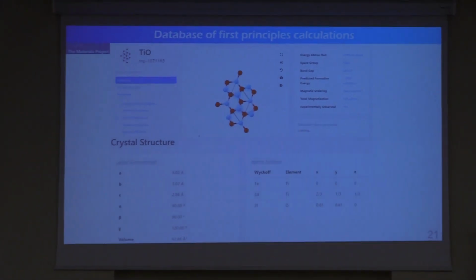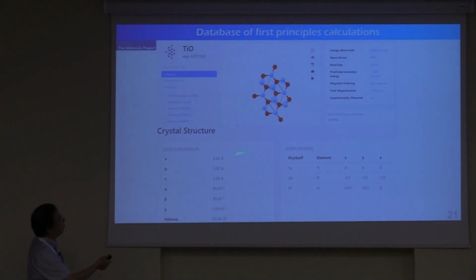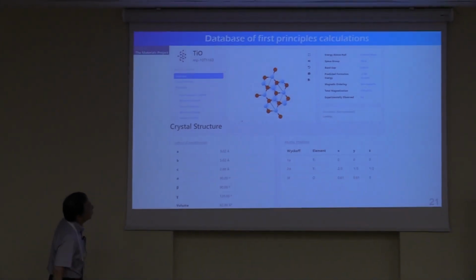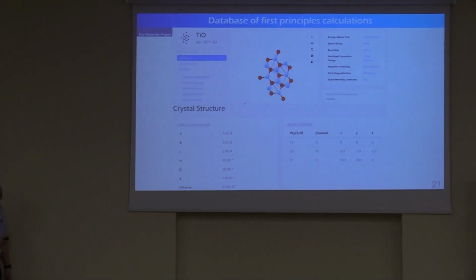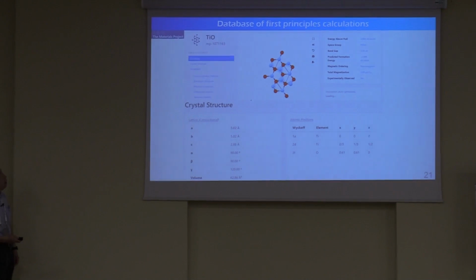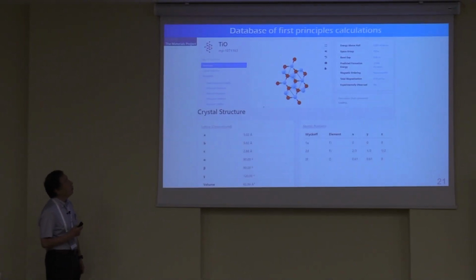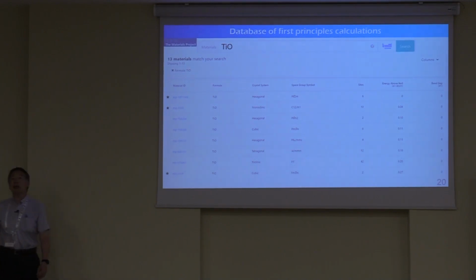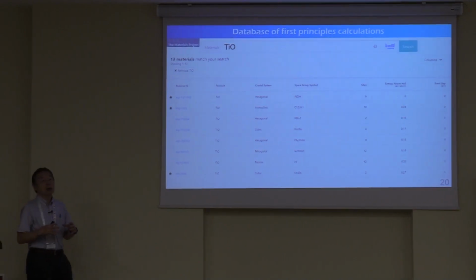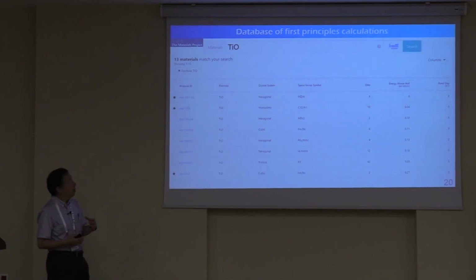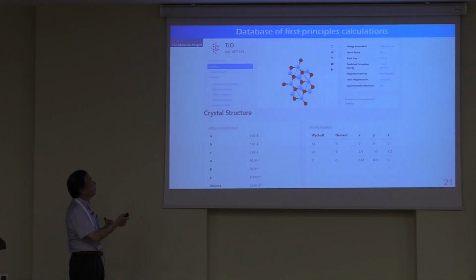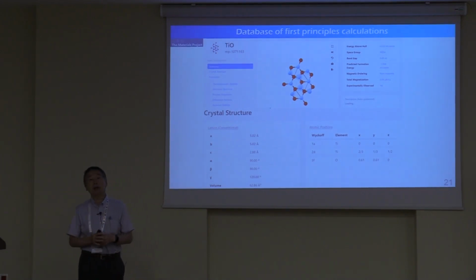The structure can also be drawn within the database. It looks like this one. And they have all lattice parameters, atomic positions, etc. The reason why this is the lowest energy structure and not the rock salt structure is not clearly known. But I can guess that rock salt structure is more easily formed. And the hexagonal structure, although this is the lowest energy structure, is kinetically forbidden. You need a very detailed, very careful experiment to obtain this material.